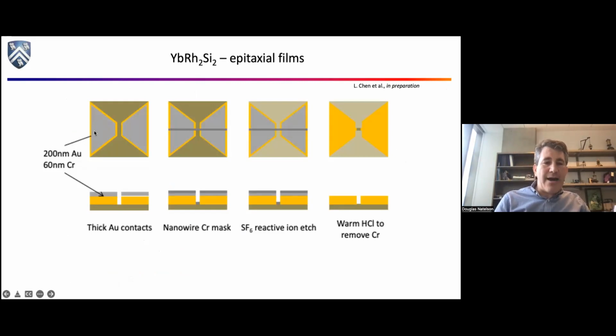So, you know, you can put down basically a protective coating of the gold, which is going to eventually be our contacts, but you've got some chrome on top just as a mask. You can have a chrome strip here. And now you're going to throw this whole thing in an etching machine where you can eat the ytterbium rhodium 2 silicon 2, but nothing else. And then you can strip off the chromium by dipping this whole thing in warm hydrochloric acid, which again, was an interesting way to figure that out. But in the end, you end up with a device that is a little snippet of wire, right?